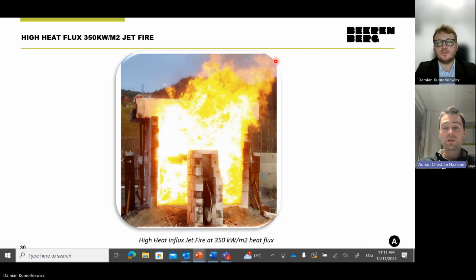In a jet fire, and especially in a high heat flux jet fire, you can have anything from 1000 degrees to 1450 degrees oscillating up and down. So it's really on the edge of what removable PFP systems can do. In some tests, you go beyond the point where steel starts to melt. So not every fastening component can do it, and it's really pushing the limits of both what's physically possible to generate in terms of heat in a fire, and also what's possible for a system to withstand.